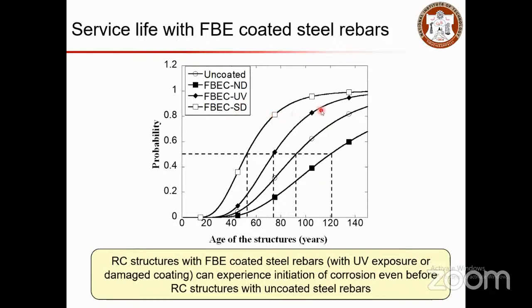So when you have surface damage and ultraviolet exposure, the performance is going to be less compared to your uncoated bar itself. The probability of failure with respect to the age of the structure will be more when you have damaged epoxy coated rebars. So the rebars with coating will perform better only when you take care of them properly, with no damage. When you can give proper control or care to a rebar, then you can go with epoxy coated rebar. If you cannot take care of it, then it's better not to use it, and you can go with the conventional rebar, so that the consequence will be less compared to the consequences of using rebar with damages.